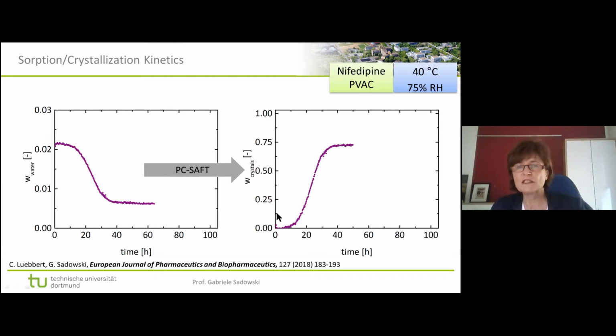And this is what you see here. And then you can see how long it took to crystallize. So it was about 30 hours. So after one day, it's done. Of course, this depends on the system. This is what I want to show you. This is nifedipine and PVAc, polyvinyl acetate, a less hydrophilic polymer, at the accelerated storage conditions.